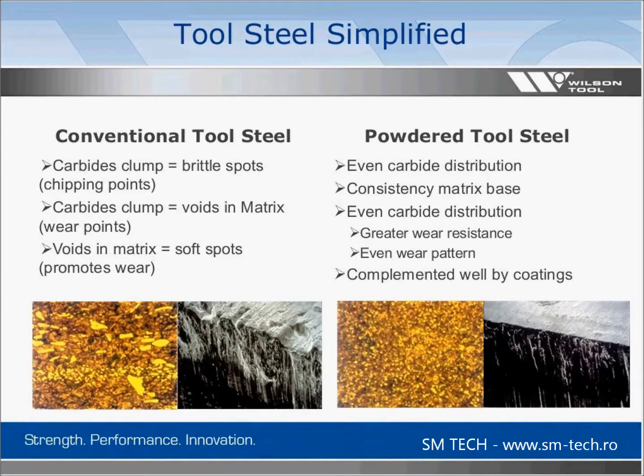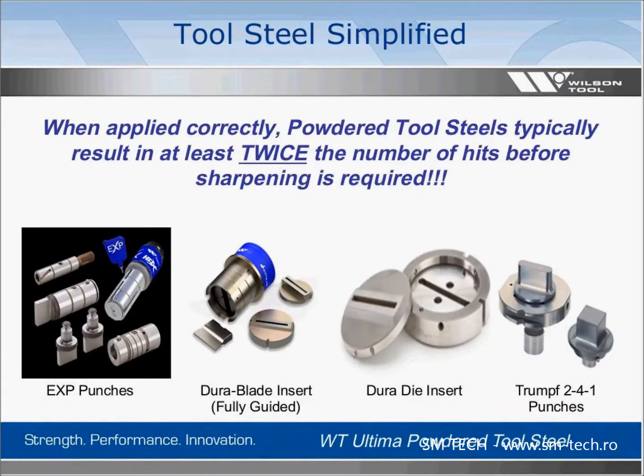In your powdered tool steel or powdered metallurgy, there's a much more even carbide distribution throughout the tool steel. If you look below, you'll see the yellow, which are the carbides, very small and very dotted throughout. That consistency in the base of the matrix creates a much greater wear resistance and a much more even wear pattern. Also, both conventional and powdered tool steels are well complemented by coatings. However, with the additional life you get from a powdered tool steel, the coatings are a great complement to get the most bang for your buck. When applied correctly, powdered tool steels typically result in at least twice the number of hits before a sharpening is required. That comes down to the carbide distribution throughout the tool steel.